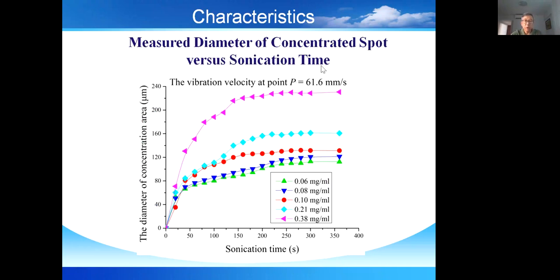This is the measured diameter of the concentrated spot versus the sonication time. From this figure, we can see that it takes several minutes to form a stable concentration spot. Also from the results, we see that as the concentration of suspension increases, the stable diameter of the concentration spot also increases. This is because there are more nanoparticles in the droplet when the concentration increases.